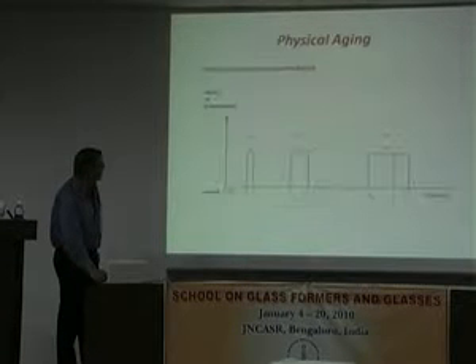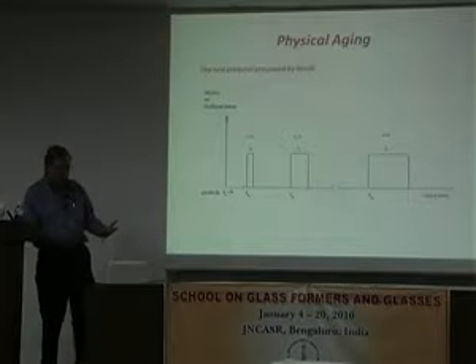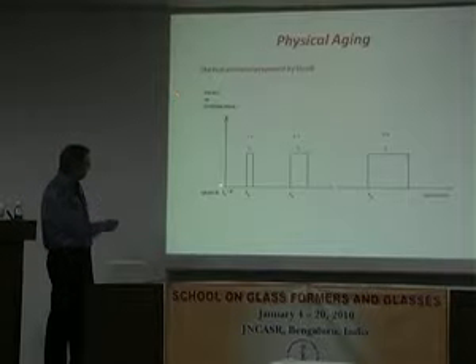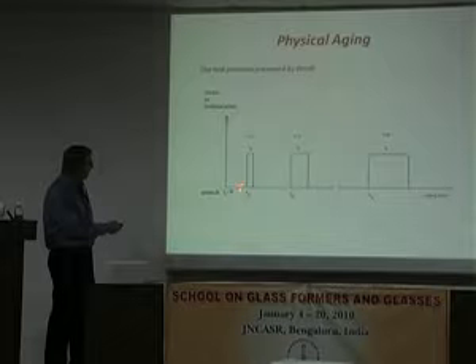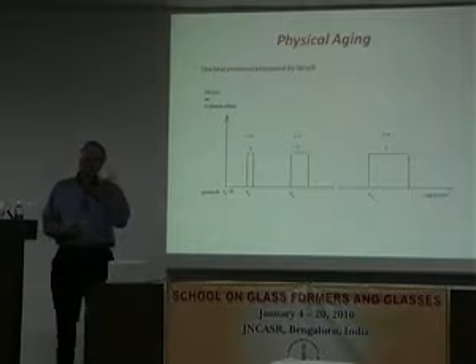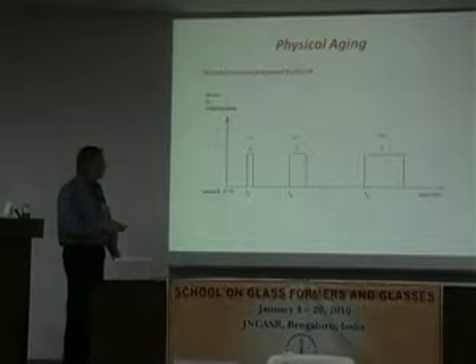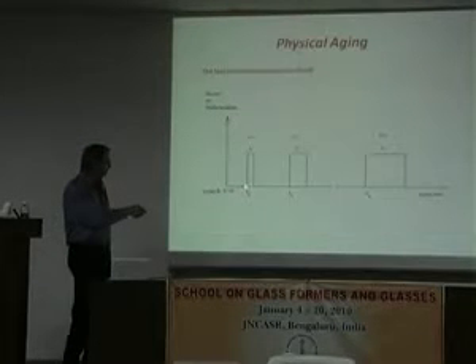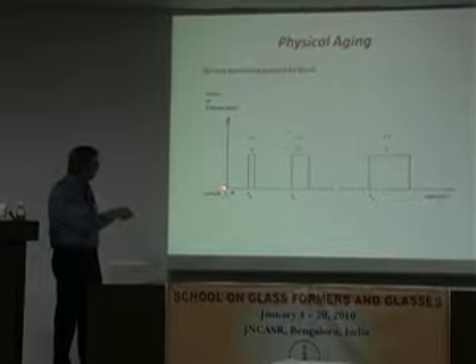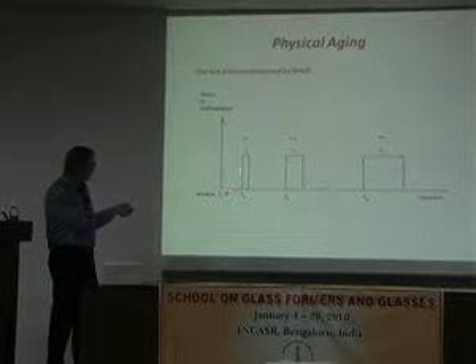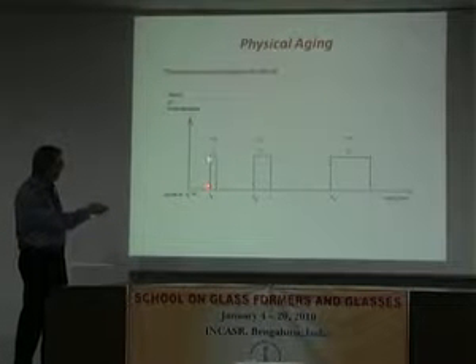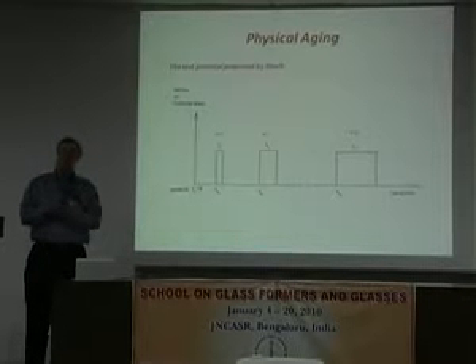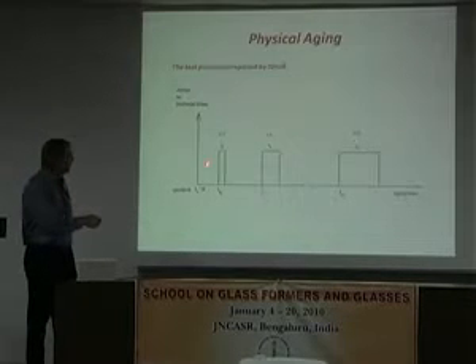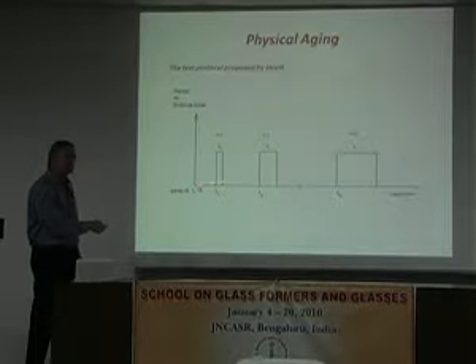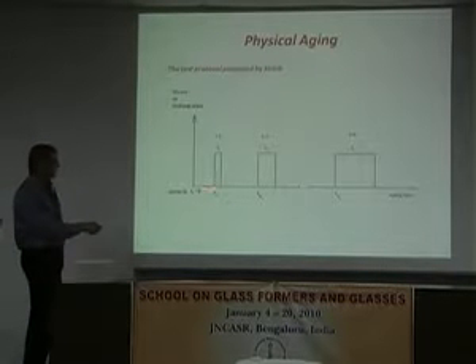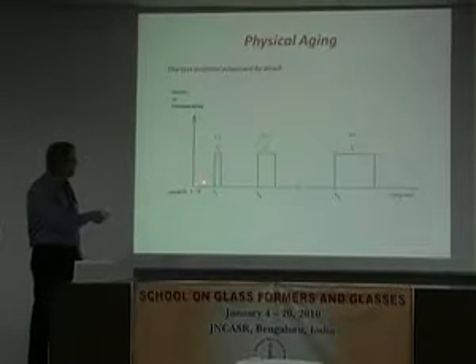And to do this, Struik actually proposed a methodology for doing it, and then he justified it, okay? The proposed methodology is you do your quench, and then at some aging time, now this is t_e, you'll see a lot of people in this community use t_w for waiting time. Struik used the term t_e for elapsed time. And this elapsed time, the first one, he would have it be, let's say, an hour. And then he would put a mechanical stress or strain on the sample, and then he'd hold it. So he's doing a stress relaxation or a creep experiment. But he always holds that this t_i is always less than 10% of the waiting time, or aging time, or elapsed time. Okay? And the reason for that is because you don't want whatever the structural recovery is doing.